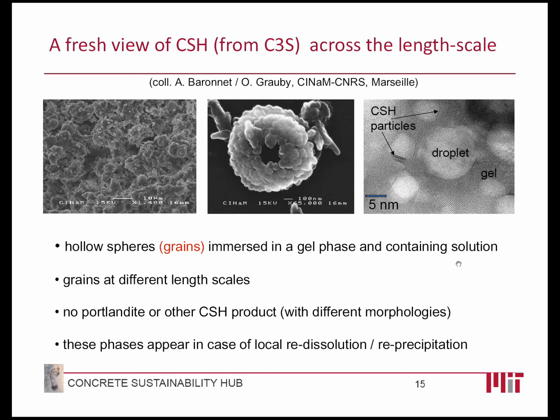Okay, these are three micrograph views of CSH at different scales. The first plot on the left is at the scale of 10 microns. You can see CSH looks like a collection of cauliflowers stuck together. If we zoom in on one of those little blobs, you can see that this blob is also made of little grains. Now we're at the scale of 100 nanometers, this is the middle picture.